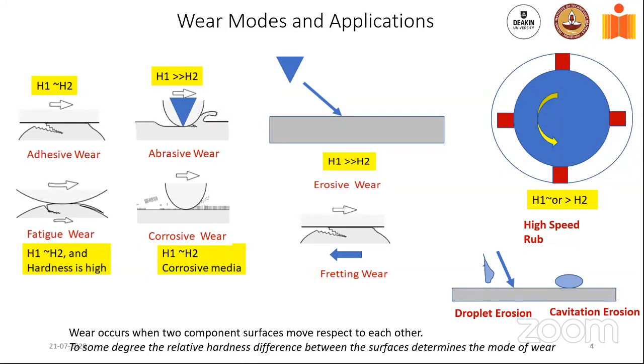Then on the top right, you actually see two circles, and you see these red objects which are essentially blades on these circles. And this represents a cartoon of what a turbomachinery does. The blades are rotating, mounted on the rotor. They're rotating concentrically with respect to the casing, except that it's not always concentric. There can be an ovality in the casing for different reasons. The rotational orbit may itself go out of whack and you can have a rub taking place. And this takes place at a velocity of Mach 1 or more. And this kind of wear is also quite significant and severe. And then on the bottom right, we have droplet erosion and cavitation erosion, which is because of either air bubbles in liquid or just plain and simple water droplets coming and hitting the sample. So these are all the different modes of wear.